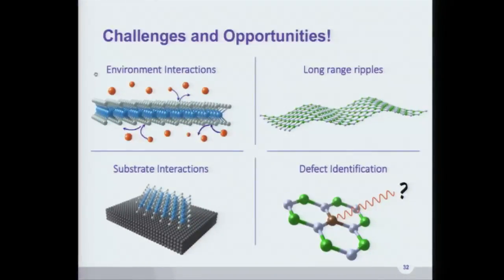And this is important because that actually changes the lifetimes in the sheet. Even if the ripple is, say, somewhere here, you would say, well, the emitter shouldn't see it. No, it does, and it actually starts to matter that we incorporate those types of effects. There's substrate interactions, and with 2D materials, something that we've noticed in particular with the work in hexagonal boron nitride is that knowing which defect it is is actually non-trivial.